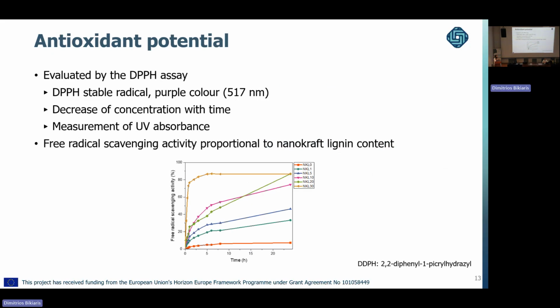And finally, the antioxidant potential was evaluated using the DPPH method. As you have seen earlier, lignin has a lot of phenolic hydroxyl groups, and this will bring antioxidant properties to the final composites. As we can see, the antioxidant properties are proportional to the content of lignin. So overall, in this first series of materials with nanokraft lignin, we have very nice mechanical behavior and also some nice antioxidant properties.